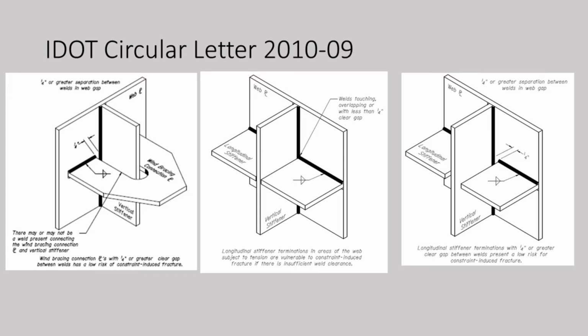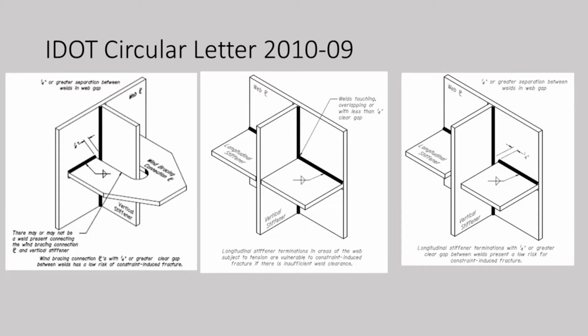You can see this stiffener's clipped there, but I think that was done for photographic purposes. These things usually are squared off on their ends. The one thing that I wanted to point out here, the key issue, is this quarter-inch distance between the vertical and horizontal fillet welds. The guidance indicates that if that distance is less than a quarter inch, or if the fillet welds are touching, then you could possibly get constraint-induced fracture.